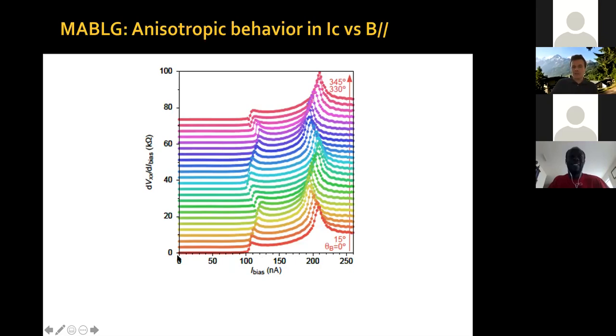You can see that, and the different color traces are the different angles of the magnetic field in steps of 15 degrees. You can see that there is this switching current. The system here has zero differential resistance, and then it switches, okay? So out of the superconducting state, this switching current evolves with twist angle. It has two maxima, so this has C2 symmetry, okay?